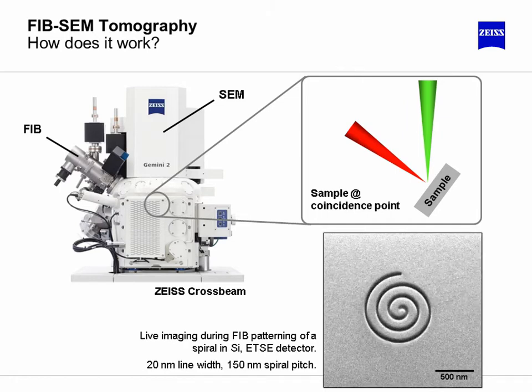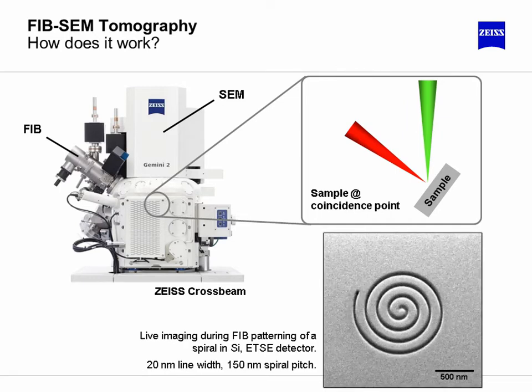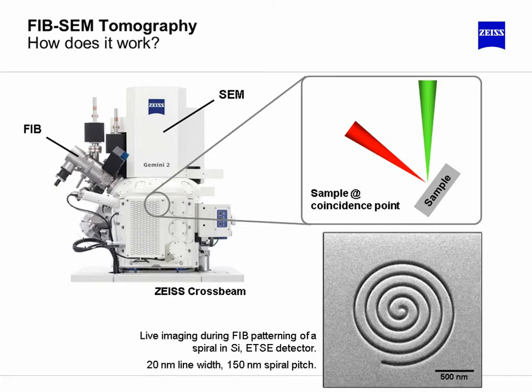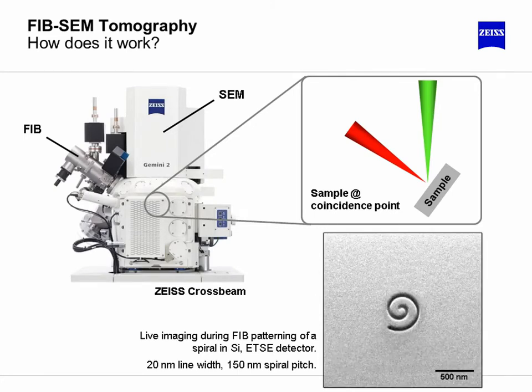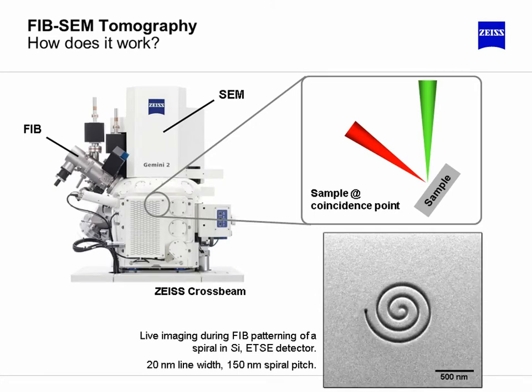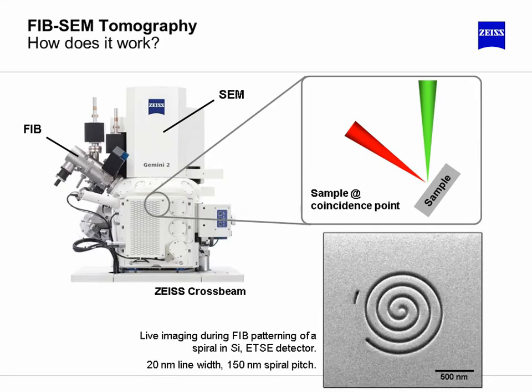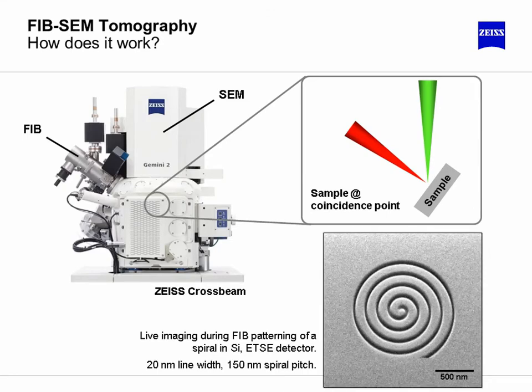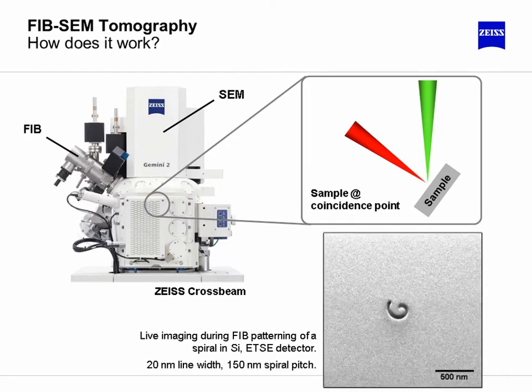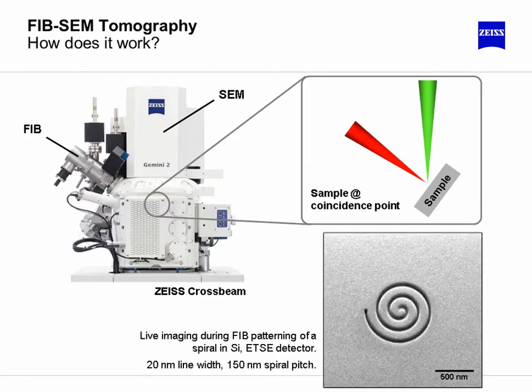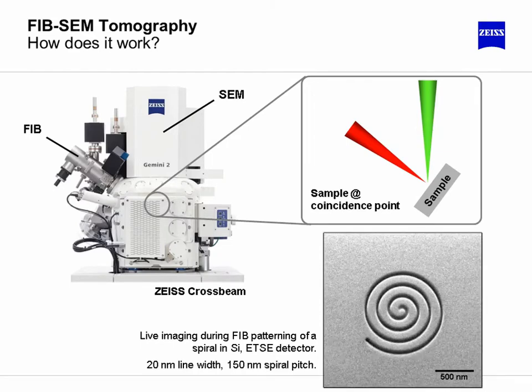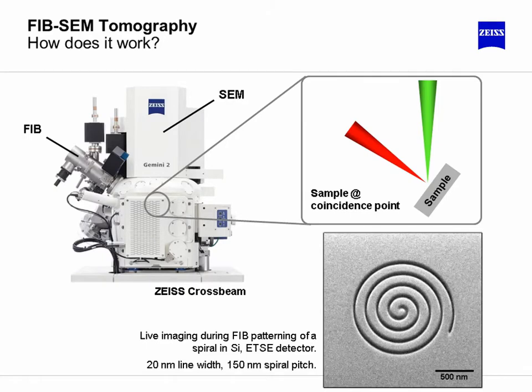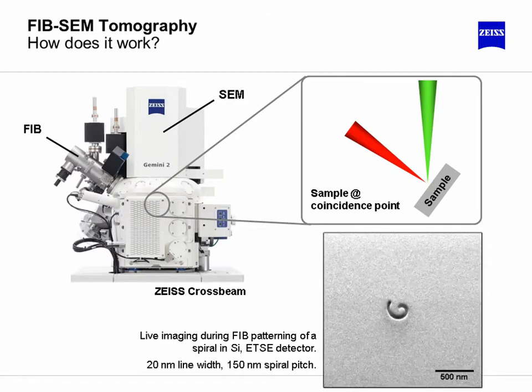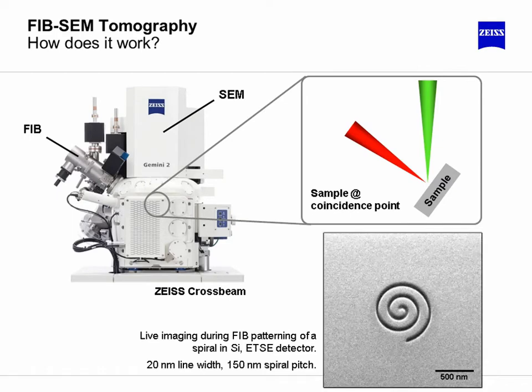The ZEISS crossbeam is designed in a way that the patterning process can be imaged live, as you can see right now, at the best instrument's resolution with any of the available detectors. You can see how the focused ion beam is being used to machine a spiral onto a silicon substrate. The spiral has a spiral pitch of 150 nanometers and a line width of 20 nanometers.